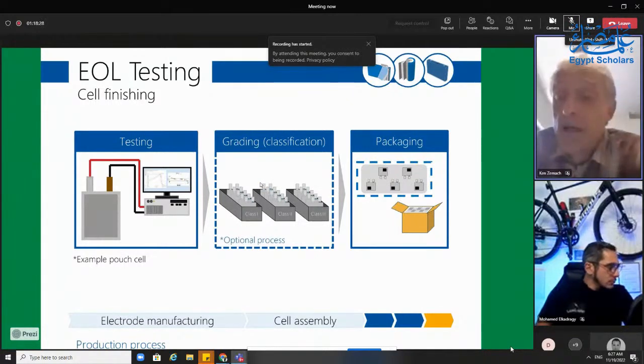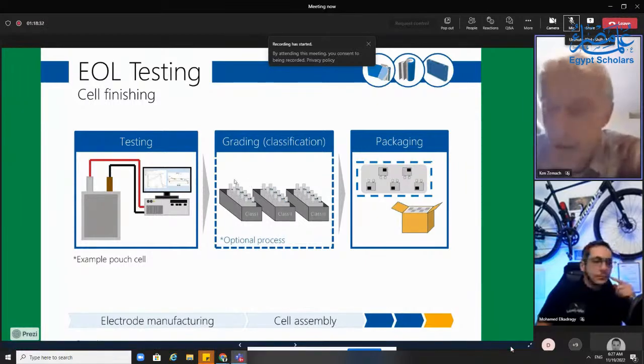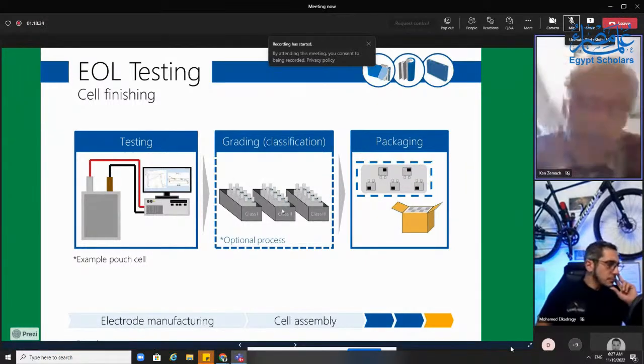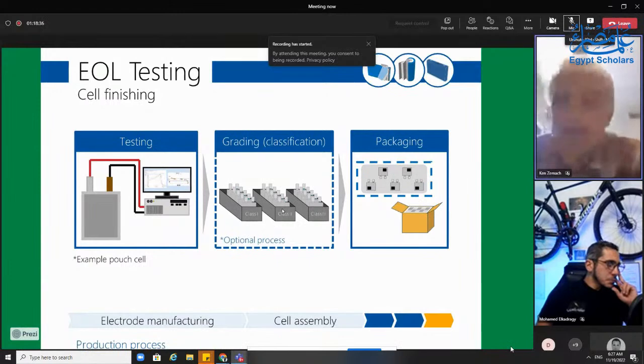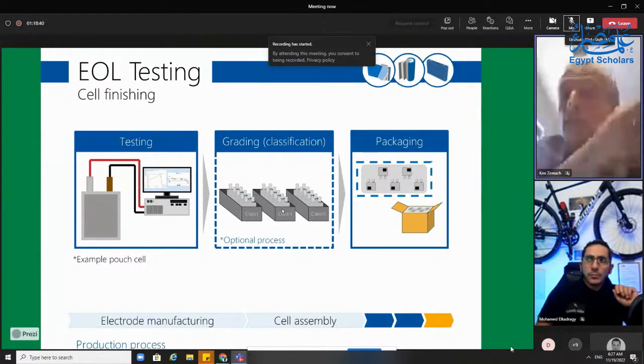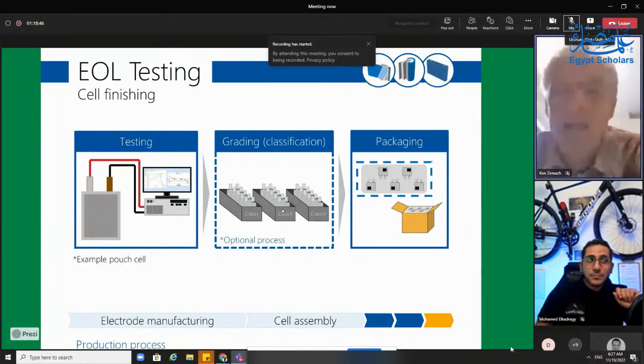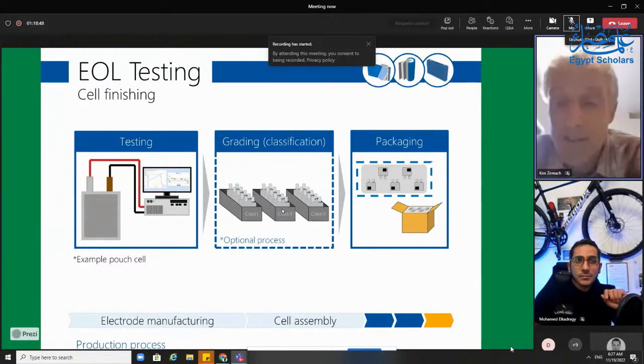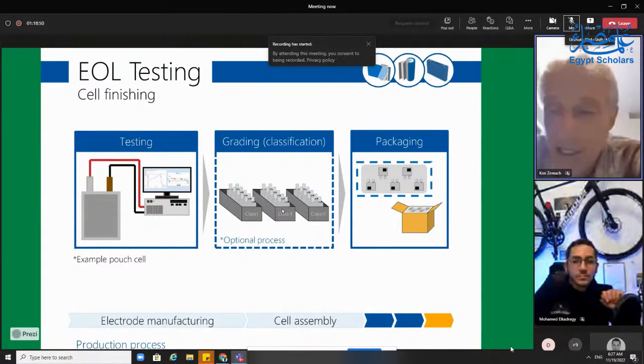Was there enough material? And all these cells get weighed multiple times. So you confirm that you got enough electrolyte in, because you know how much your can weighed, you know how much your jelly roll weighed. You confirm that the voltage is right. You confirm that there hasn't been too much self-discharge, which would indicate you have a short inside the cell. You look at the internal resistance. There's a million things that you check. But you've been checking these things all along.